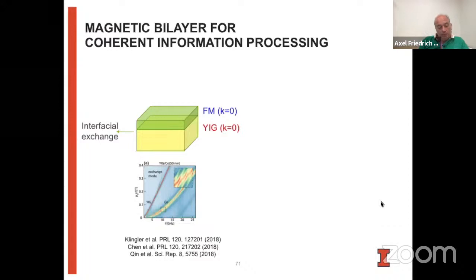And so there were a whole bunch of nice examples, for example, from Matthias Weiler in Munich and others, where you combine yttrium iron garnet with another ferromagnet. And if they share a common interface, they have, of course, direct interfacial exchange coupling here. And here you see measurements where they have cobalt on top of yttrium iron garnet, and you see all kinds of mode crossings of lots of quantized spin waves in the yttrium iron garnet that cross over this cobalt ferromagnetic resonance mode.